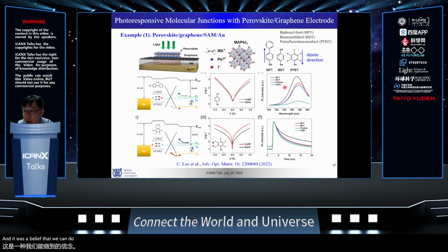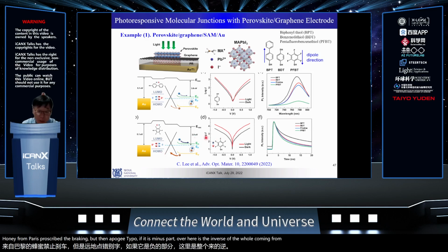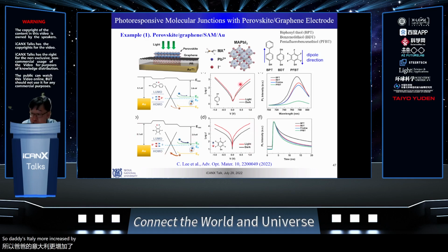And with the molecule, we can do a little more variation by using different dipole directions. In the up direction there is almost no dipole, while in the down direction the electric field will enhance or block the hole transmission. For example, here the dipole plus is up, so the molecule somewhat hinders the holes coming from the perovskite to the graphene. But with the opposite dipole, the minus part over here enhances the holes coming from the perovskite to the graphene. So the increase upon shining is larger in one case and smaller in the other. This is one idea of how we can utilize a heteroelectrode structure.